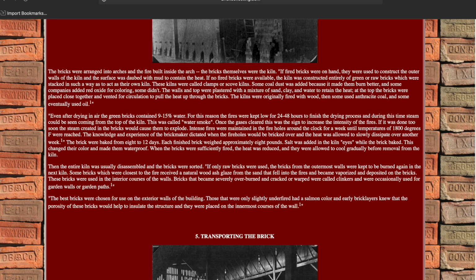If only raw bricks were used, the bricks from the outmost walls were kept to be burned again in the next kiln. Some bricks which were closest to the fire received a natural wood ash glaze, and sand that fell into the fires became vaporized and deposited on the bricks. These bricks were used in the interior courses of the walls. Bricks that became severely overburned and cracked or warped were called clinkers, and those were occasionally used for garden walls or garden paths. The best bricks were chosen for use on the exterior walls of the building.